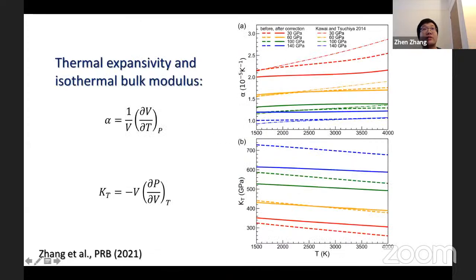Here are the obtained thermal expansivity and isothermal bulk modulus. Our obtained thermal expansivity is nearly temperature independent, which is an indicator of the importance of anharmonicity. The relatively stronger temperature dependence and overestimation of thermal expansivity, especially at low temperatures, as reported by previous studies, which are shown as dash-dot curve, is an indication of insufficient capture of anharmonicity.